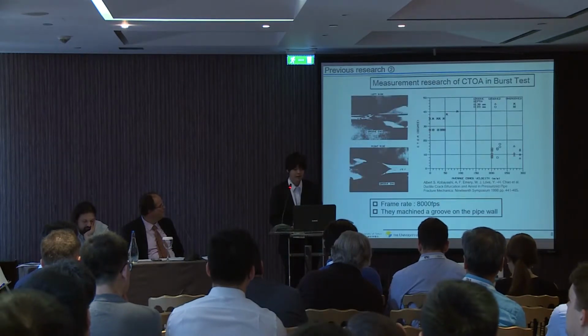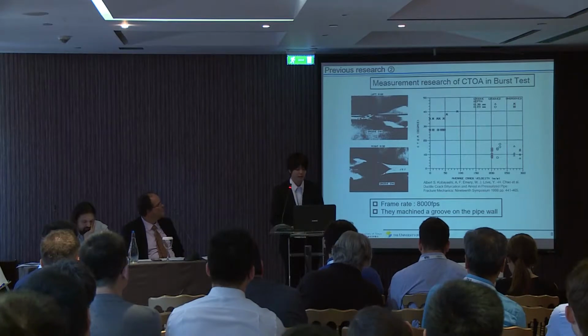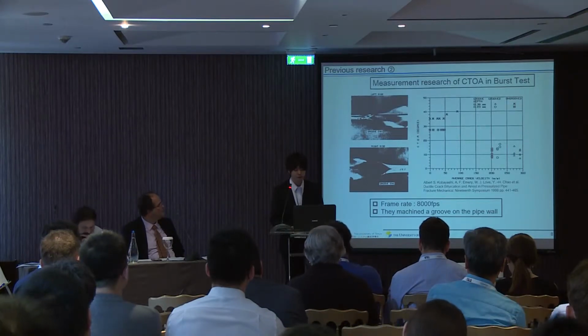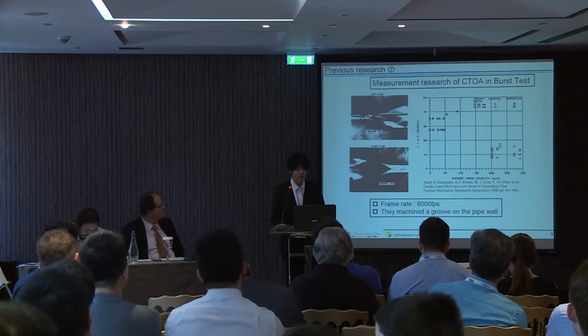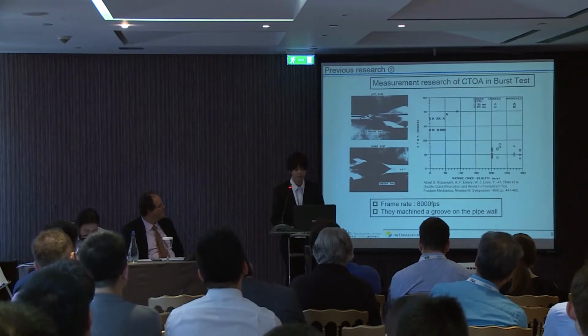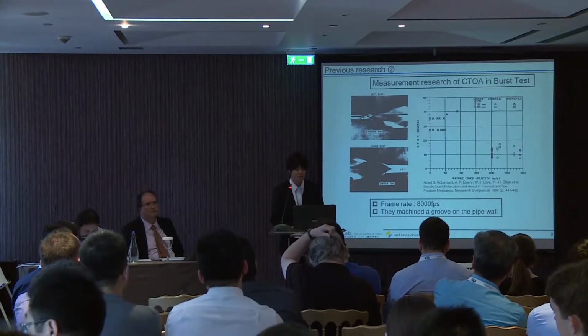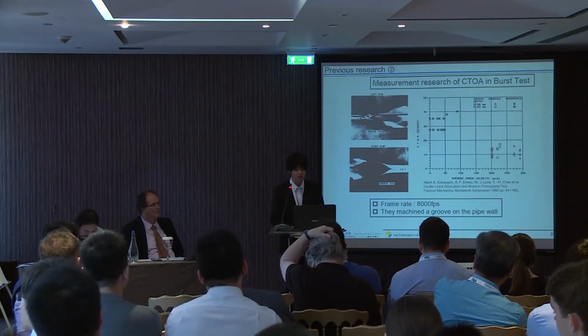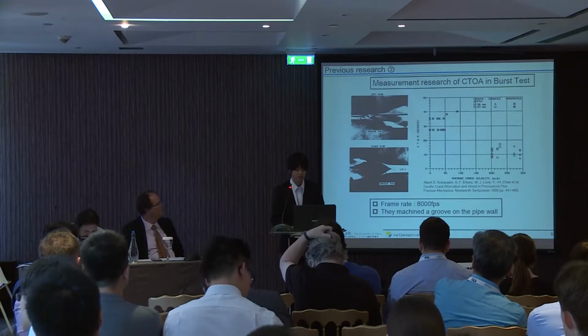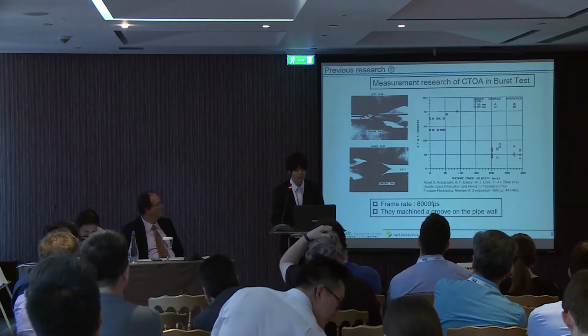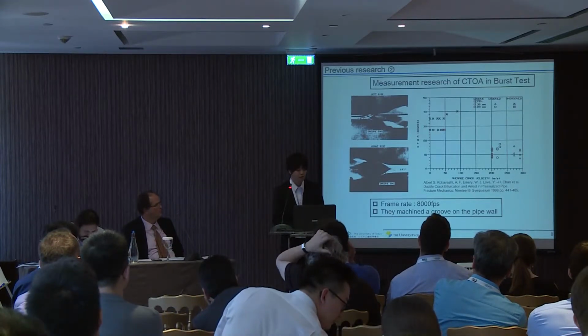The following study is a study of CTOA of burst test by Albert Kobayashi. This is the only CTOA measurement of burst test we know. They observed a crack velocity dependency of CTOA resistance value. However, the reliability is not high from the point that the number of frames per second of the camera is small.